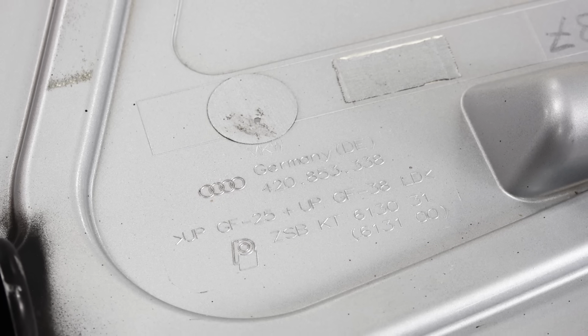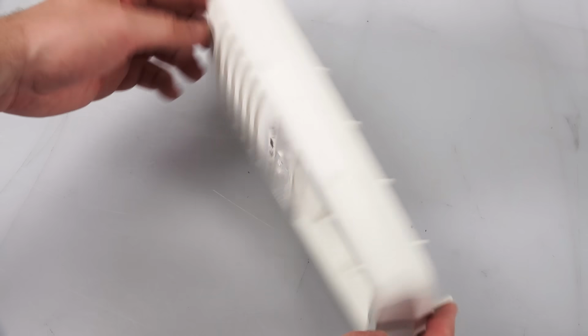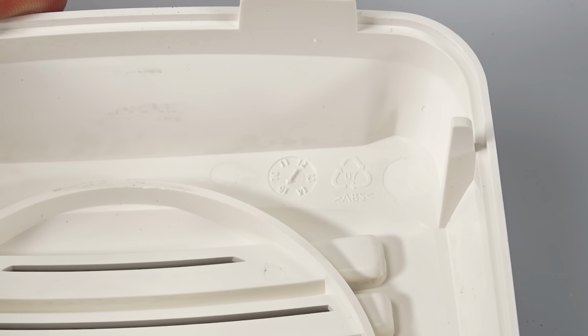If you take a look at the back of the part in the code, it will normally tell you what it's made from. If it says it's ABS, then unfortunately the styrene in the resin is going to partially attack and dissolve the surface, which is going to cause them to fuse together. If you did need to pull a mould from an ABS part, you can do this, but you will first need to coat it with a pattern coat or an epoxy.